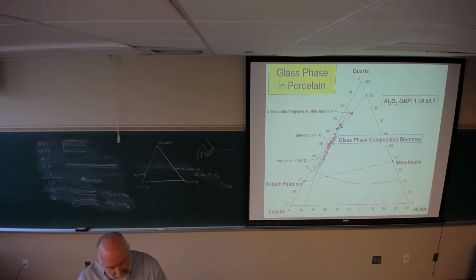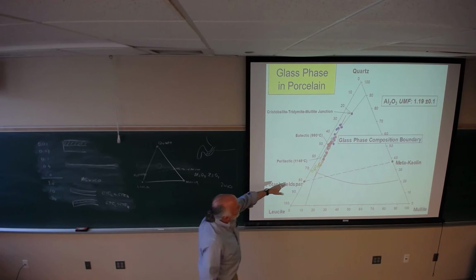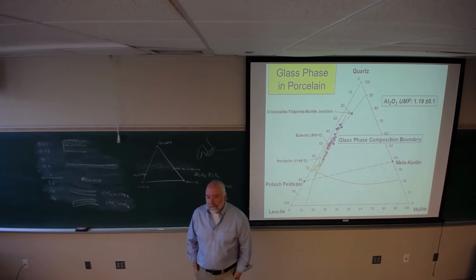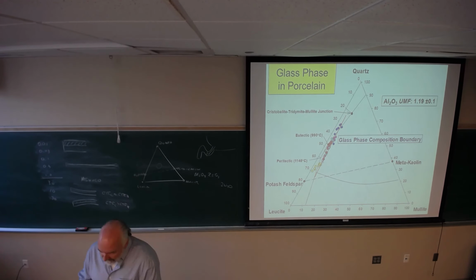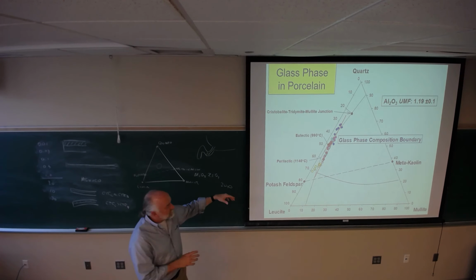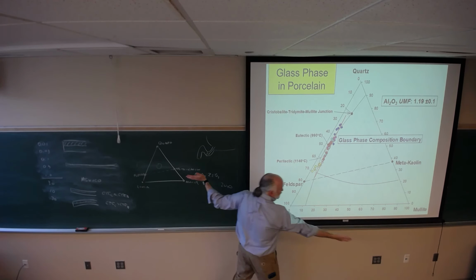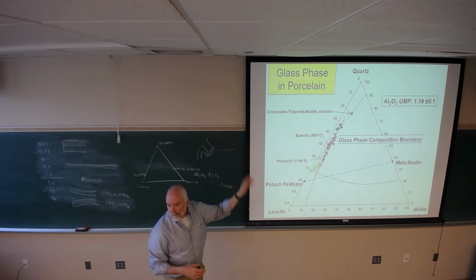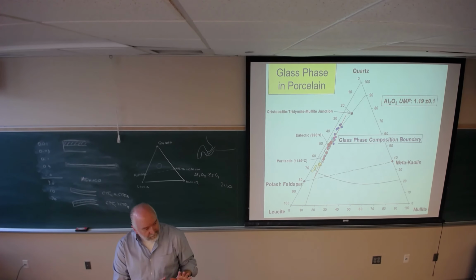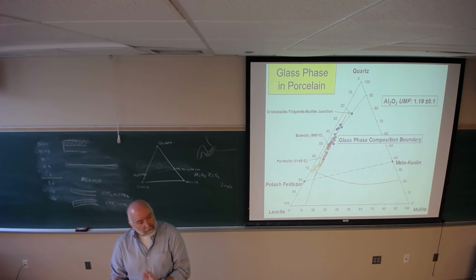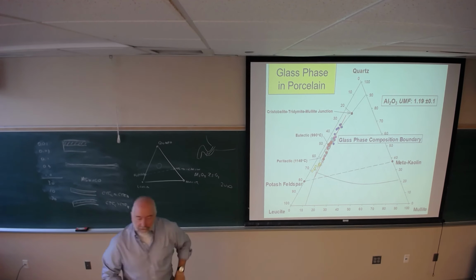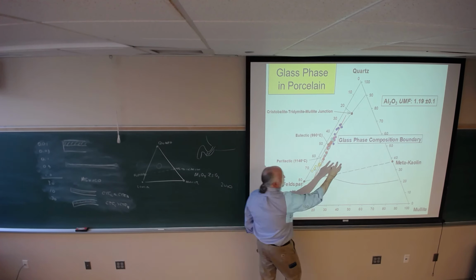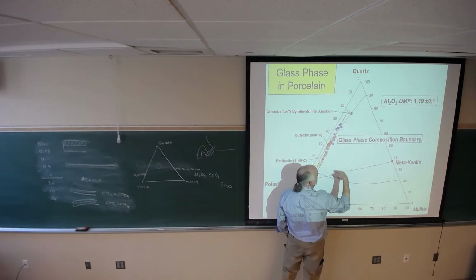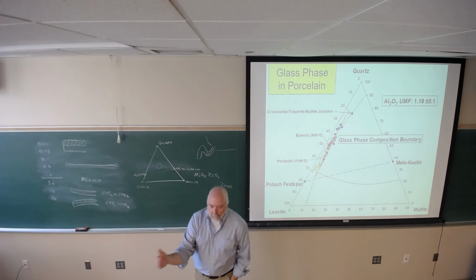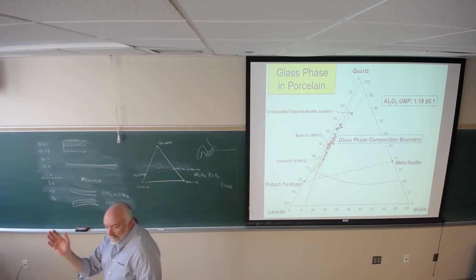And the reason it's fixed is because we argue that this is the glass formation boundary in the system. In other words, if I am to the left of this boundary, and recognize this is a small triangle of a larger diagram, if I'm to the left of that boundary, I have good glass formation behavior. And if I'm outside of that boundary, I get a glass ceramic, if you will, or I get a material that wants to crystallize on cooling. And where do I sit? My compositions sit in here, and I'm in the mullite phase field, so that means I'm going to form mullite on firing. There's no way around it because I sit in the mullite phase field.